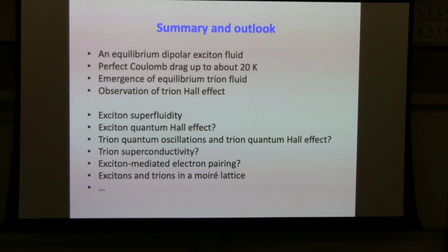Hopefully this platform can open up an interesting way to study much of the physics that one can foresee in the future. For instance, whether we can probe exciton superfluidity, whether we can engineer the system to exhibit a quantum Hall effect for the excitons. And as Steve mentioned, whether we can see trion quantum oscillation by improving the sample, or even the trion quantum Hall effect. Trions are fermions. They may be able to pair up as well at low enough temperature. Maybe a trion superconductivity can be realized. And so far, I have not told you anything about moiré. You can still imagine that I can replace one of the layers, the electron or the hole layer, with a moiré lattice. Then we can start thinking about putting excitons in a lattice and try to do something like the AMO community would like to do. So with this, thank you for your attention.